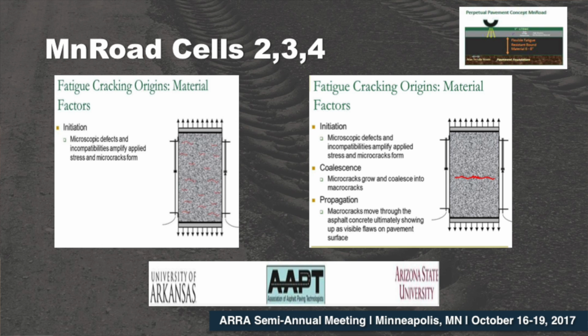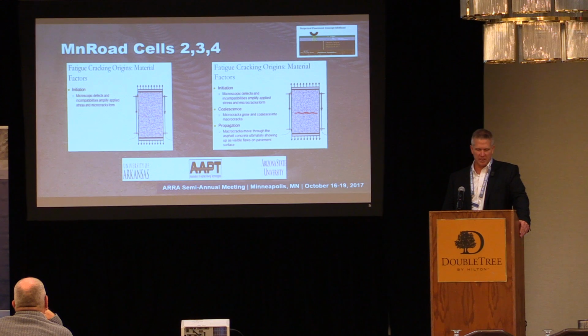And one of the things that I've been looking at, found some research work done by the University of Arkansas, and might have been Andrew's work, not sure, but AAPT and Arizona State University. We're looking at fatigue cracking origins, and what they looked at was the initiation and how that crack coalesced and propagated through material. And I think what we're seeing with this recycle in place material, it does not behave like a hot mix material.